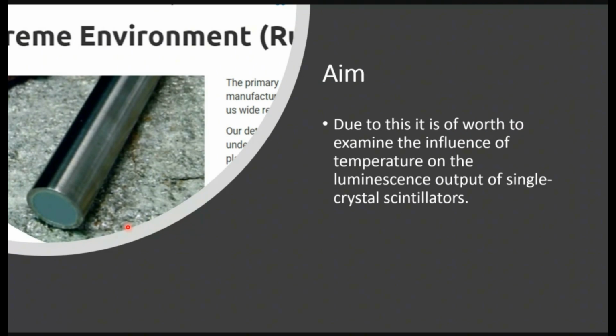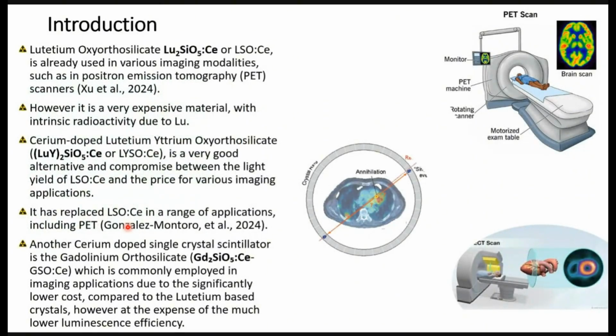The aim is, of course, to examine the influence of temperature on the luminescence output of single crystal scintillators. In this study, we examined three materials. All three materials are co-doped with cerium, and they are commercially available and applied to various applications. In medicine, we have used them in positron emission tomography scanners. The first material contains lutetium as a base material. It's the lutetium oxyorthosilicate. It is a very effective material with high luminescence efficiency, high light yield, but it is very expensive. Lutetium is very expensive, and also lutetium contains intrinsic radioactivity. This is a drawback for a system.